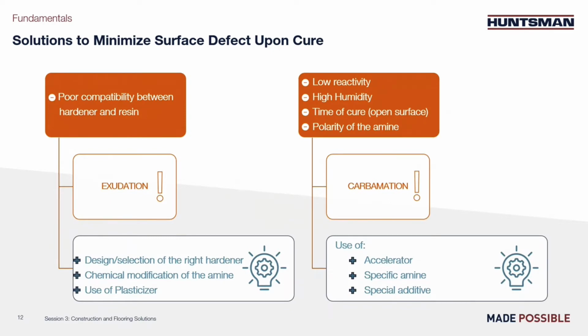In this slide, we would like to explain the reasons and solutions to diminish this surface defect. The goal is to favor the compatibility of an epoxy resin and of the hardener. By doing so, you diminish the risk of exudation. In the worst case scenario, resin and hardener will not be compatible at all, and you could get two phases, so cure cannot really happen. To help the compatibilization, we have designed hardeners in a way to support the miscibility with the resin. In effect, we modify the amine, and in some cases, we use a plasticizer like benzyl alcohol.